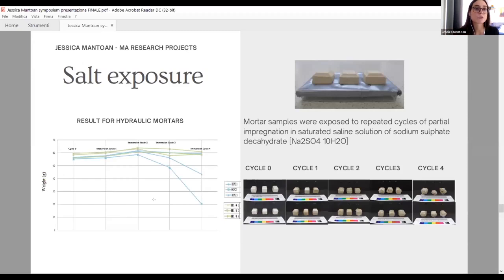The final test that I carried out was the assessment of the salt exposure. I decided to put my mortar samples half covered with a saturated solution of sodium sulfate salt. And as you can see from the photographic record, but most of all from the graph, the sample containing no barium hydroxide, after the second cycle, has a terrible disruption of the material due to the formation of the soluble salt in the lattice of the mortar. And that is particularly visible in the graph, but most of all in the picture, where in the first cycles of impregnation, mortar not containing barium hydroxide is completely destroyed, while mortar containing barium hydroxide presents a much better shape.